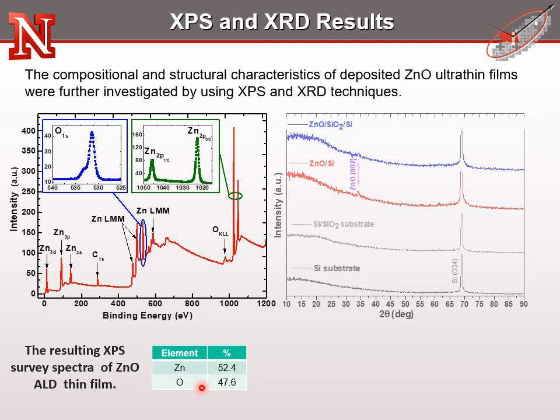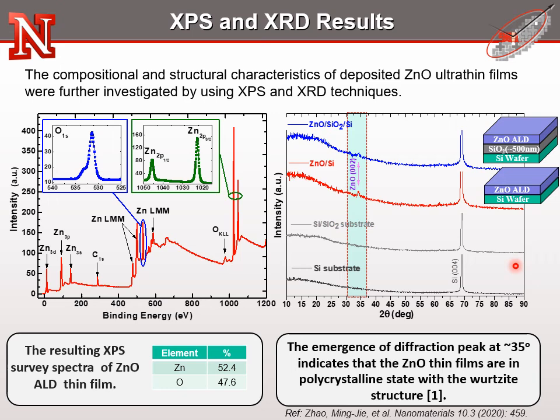As a complementary study, we also performed X-ray photoelectron spectroscopy for elemental identification of our fabricated thin films. We find that only zinc and oxygen are present in the film, with a chemical composition of 52.4% and 47.6% respectively. These values are excellent indicators of the expected stoichiometry of zinc oxide thin films. Moreover, we also performed XRD measurements of zinc oxide thin films fabricated on both silicon wafer and 500 nm silicon dioxide substrates, analyzed before and after growth. We observed the emergence of a peak in the spectrum, which reveals a polycrystalline nature.